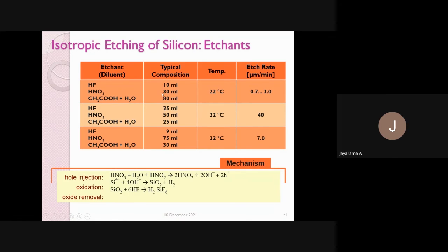Here HF, HNO3 50, acetic acid 25 ml - this combination. In one of the combinations you can observe the highest etch rate, that is 40 micrometer per minute. So optimization of etchant is more important.